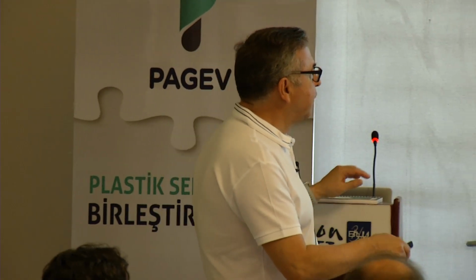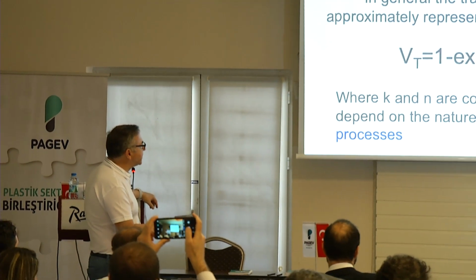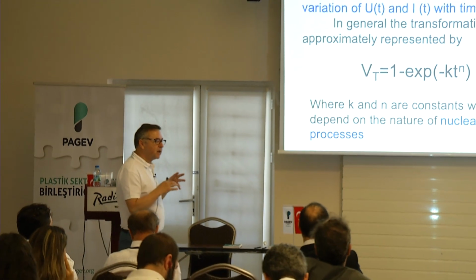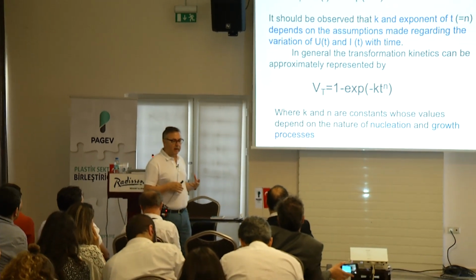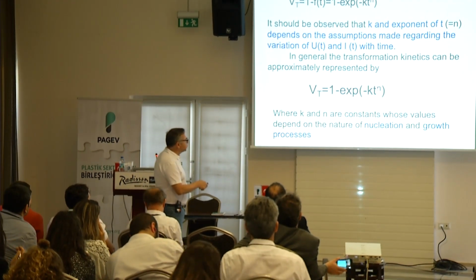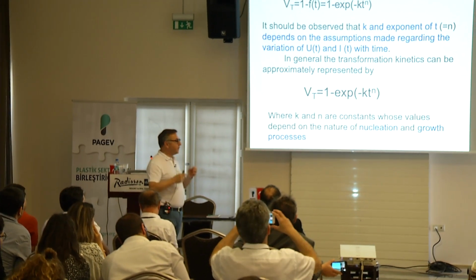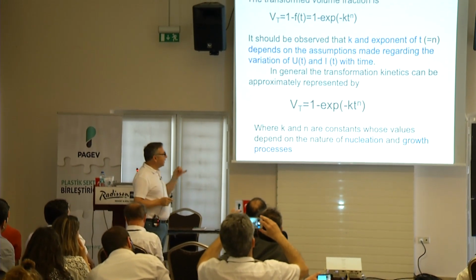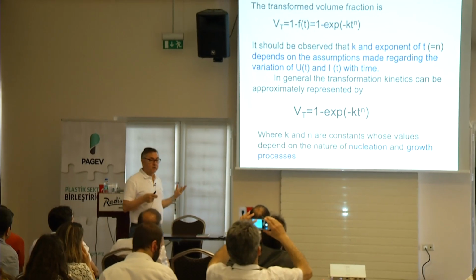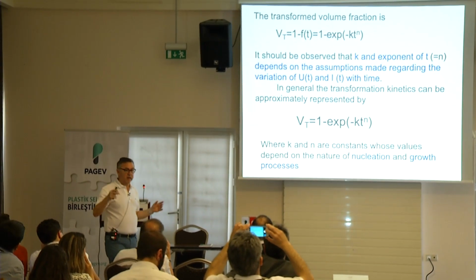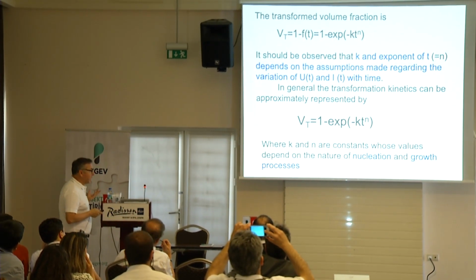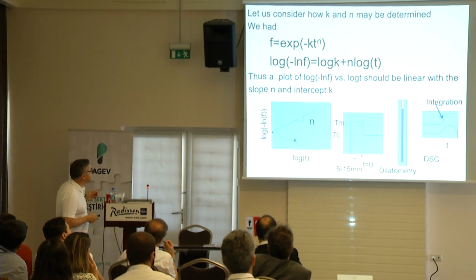All right. So the expression for the crystallization rate is given generically like this. This is 1 minus exponential k, the growth rate, and this is the growth type n. This tells you about the dimensionality of the crystal. If it's three-dimensional, it usually is large, like a sphere. If it is needle-like, it tends to be like 1. So it goes from 1 to 4 or 5 or so in industry. You can actually calculate them. I'll show you some examples.